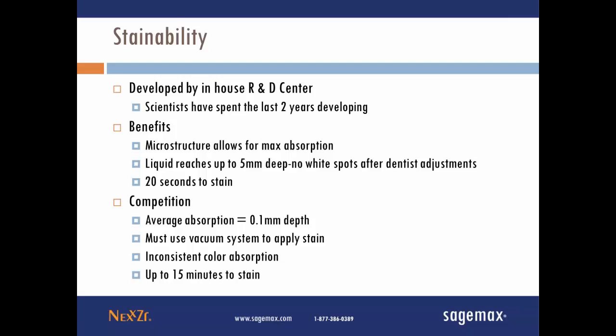Because of our microstructure and the formulation of our materials, our liquids can absorb by capillary action well up to as far as 5 millimeters in depth. So you don't see any white spots. I have some materials that I've tested from our competitors, and I can see really adverse results with white spots. We can very easily absorb colors into our material within 20 seconds. What we see from our competition is an average absorption of only 0.1 millimeter depth. As Dan had mentioned before, what we're seeing with our zirconia and in the testing that we're doing with our own staining liquids is a 5 millimeter depth.